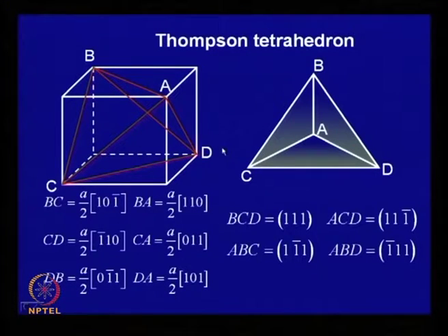We also looked at the interaction when a dislocation is moving on a particular plane and it intersects dislocations which are perpendicular to the plane. In that case, we have an interaction with a forest dislocation, and it forms jogs and steps in the dislocation line. It can form jogs and kinks, and while a kink can glide, a jog cannot glide. The jog will exert a resisting force on the dislocation, so formation of a jog also leads to strain hardening, making it difficult for the dislocation to move. But the contribution of Lomer locks to strain hardening will be even more.